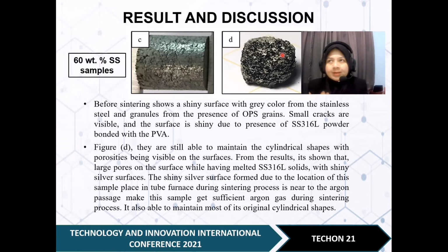Okay, in my research, I used a tube furnace, which uses argon gas supplied to the sintering process. The location of this sample is near to the argon gas supply to the tube furnace. The argon gas tends to protect the sample from oxidation.